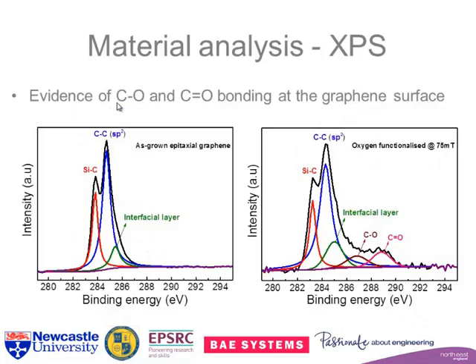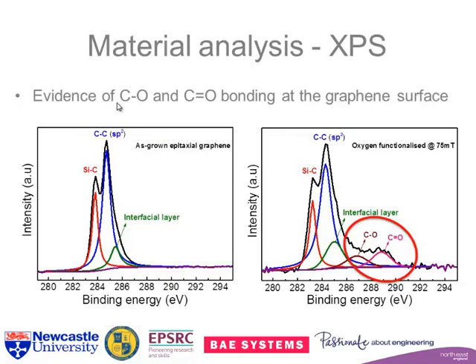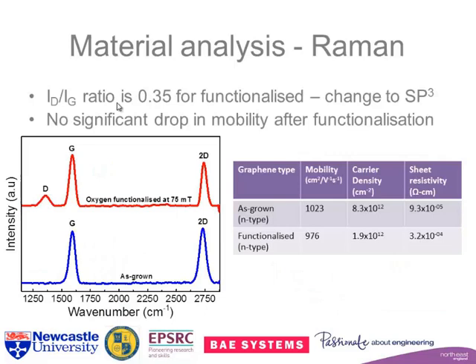So XPS, well, this is our as grown, so you can see the silicon carbide, which is the bulk layer underneath. We have sp2 carbon-carbon bonds here, and we've got the interfacial layer, which is strained, and so it's distorted. After we've had it do the functionalization, so this is 2.5% coverage, we get C-O bond and C=O bond here. And this allows us to realize that we've actually functionalized the surface nicely, and it hasn't actually got through, so we haven't got any defects. It hasn't got through, we haven't got any silicon dioxide layers either.